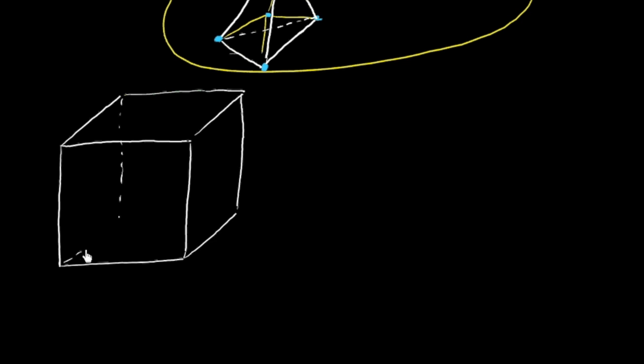So here's a cube. We're familiar with this. We've seen this face-centered cubic. We've even seen it in the rock salt crystal structure. And so what it involves is an atom at each corner. All right, and I'm going to draw here for you, depict that there's 1/8 of an atom at each corner. This is the back here now. All right, so there's 1/8 of an atom at each corner. And then there's atoms in face-centered positions, OK, front face, top face, right face. But there's also, of course, the left face hidden. So I'll dash it in. Back face and the bottom face. And so that gives us four atoms in total, OK? Four atoms from the FCC positions.